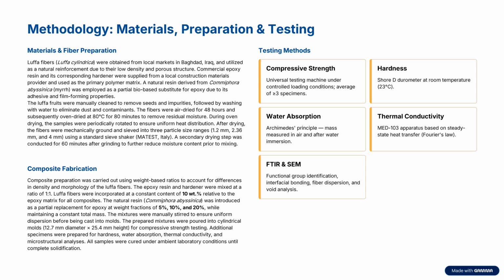The Luffa fruits were manually cleaned to remove seeds and impurities, followed by washing with water to eliminate dust and contamination. The fibers were air-dried for 48 hours and subsequently oven-dried at 80 °C for 80 minutes to remove residual moisture. During oven drying, the samples were periodically rotated to ensure uniform heat distribution.